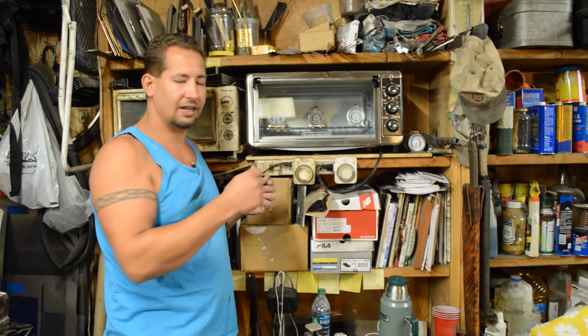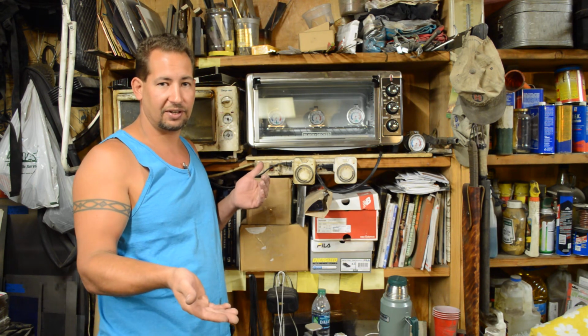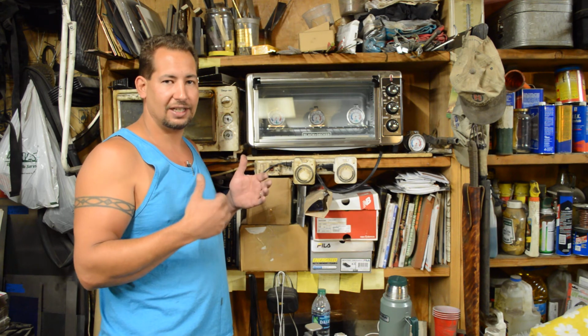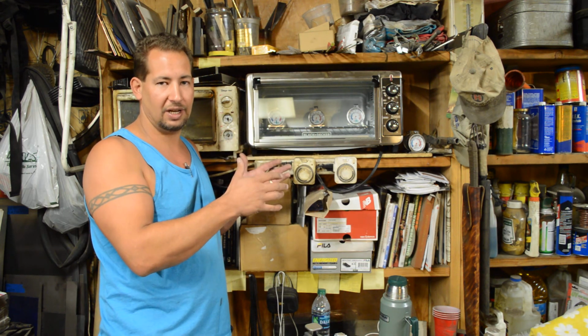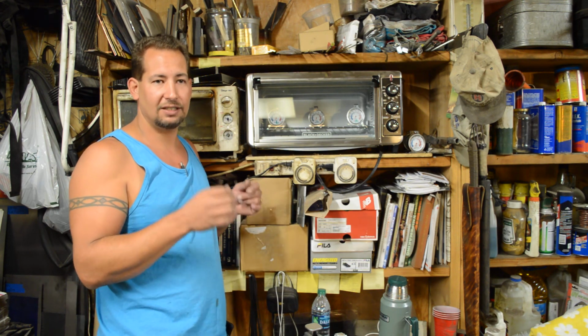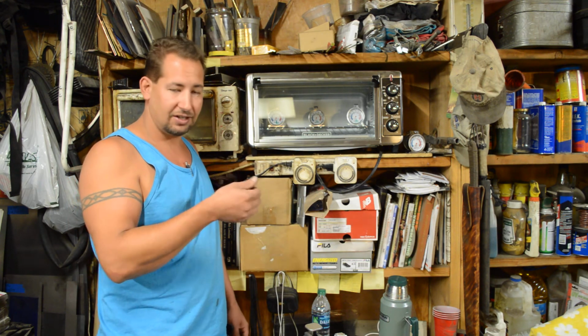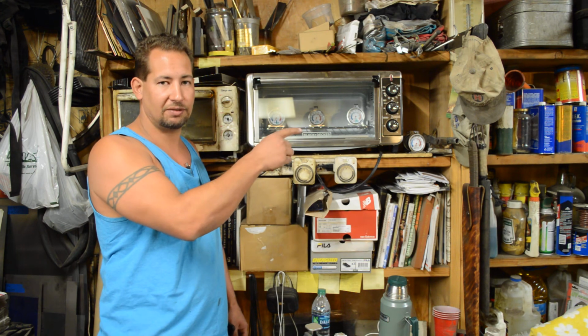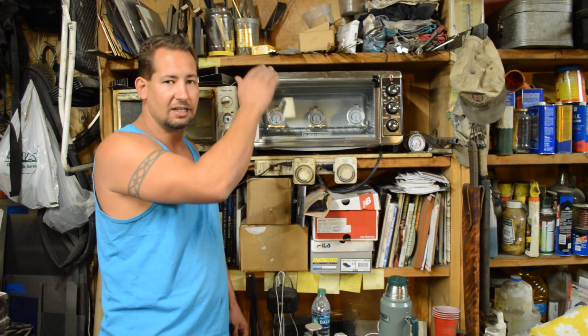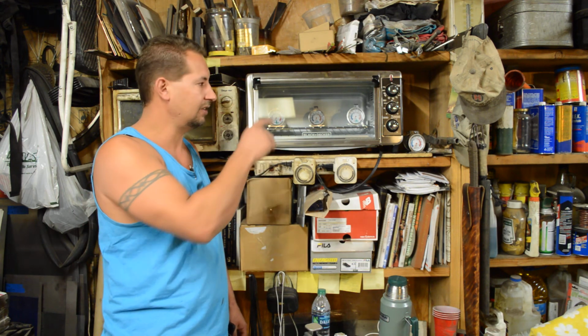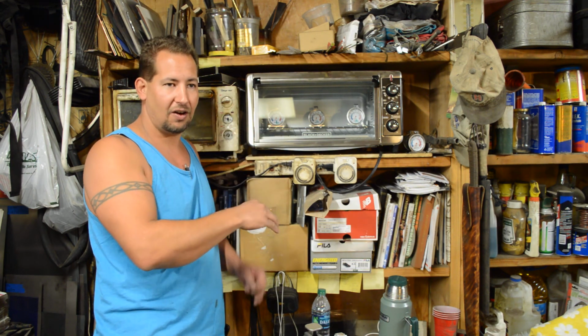So if you temper a knife in here at 300 degrees, and in the first hour it was at 250, and the second hour it's at 315, when you pull that knife out and you do your edge deformation test, that edge is going to tell you pretty much what the average temperature was. Always listen to your steel and your edge. I mean, it'll tell you what it needs if you listen to it. So I'd trust the steel way more than I would trust the temperature readings or the temperature knob. It can cycle up and down, but as long as you're calibrating your oven to your steel, then all that gets taken into account and you should have good results.